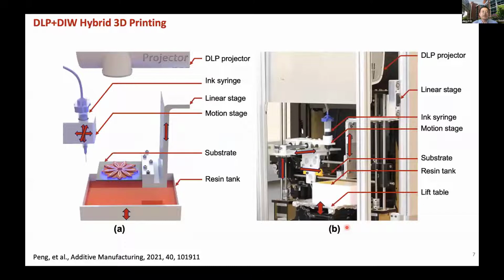Here, what we're trying to do is hybridize another approach. It's called direct ink write. Basically, we try to put together digital light processing with direct ink write. Direct ink write is very similar to fused deposition modeling. The only exception is that fused deposition modeling uses thermoplastic filaments, while DIW uses a liquid resin. So you basically extrude the resin onto your platform, and then you cure it. DIW is also a low cost approach, and you can get a DIW printer for roughly $4,000, maybe even cheaper, $2,000, depending on the dispenser that you're using to control the deposition of the ink.